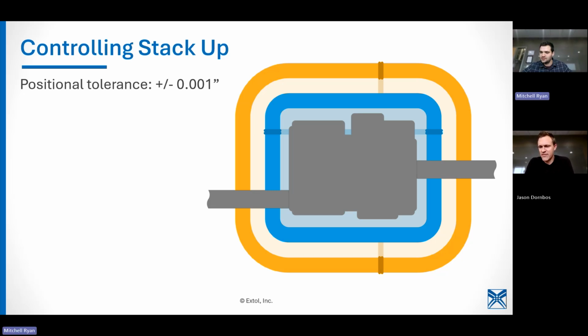Yeah. Warping in this view is taken care of by the melt process, but at some point, can you talk about how the tools themselves might hold the part square? Yes. So if you've got a lot of warp and it's even hard to get those parts into the nesting of the hot plate tooling, our welders have a feature called part pickup, and we can use that to bring the press tools together before we've melted anything. So we can use the forces available to us in the press tooling to push those parts all the way into the nest, then fire in the clamps that hold those parts into position, open the press, start the weld cycle.